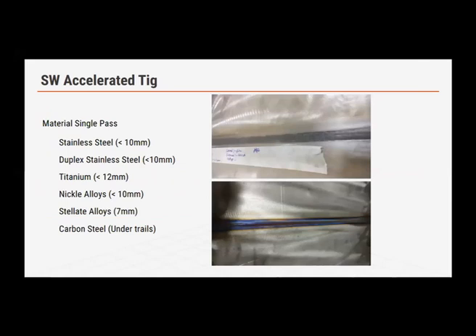What kind of materials can you weld with this? Stainless steel, definitely up to 10 millimeters. You can do square butt, no edge preparation required. Duplex stainless steel, you could do up to 10 millimeters. Titanium, we have done up to 12. Nickel alloys up to 10. Stellite, we have tried stellite alloys up to 7 mm. We can do higher. We have much more current available, but we didn't have the material at higher thicknesses.